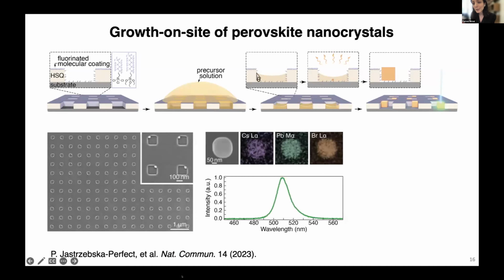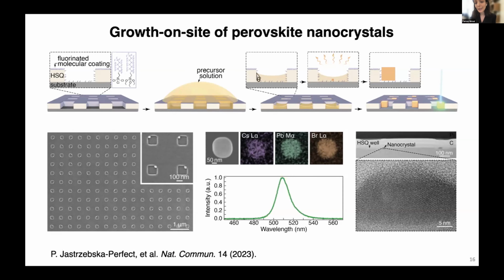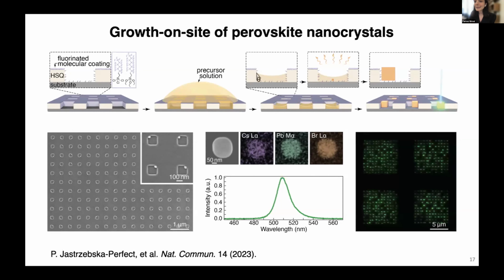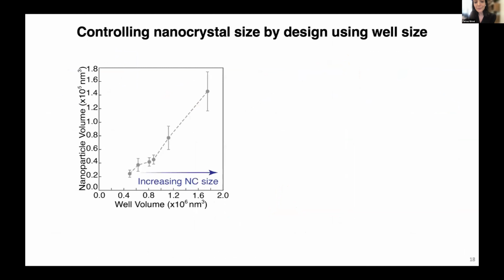As well, using optical spectroscopy, we have an approach for characterizing the material further, both independently and afterwards when integrated into a device. Using cross-section imaging under TEM, we can characterize the crystal structure of the particle that we have, and in this case confirm that the particles formed are actually single crystalline. Again, the process is scalable, so suited for device integration. So we also need more high throughput and larger area characterization techniques, which are often optical in nature.